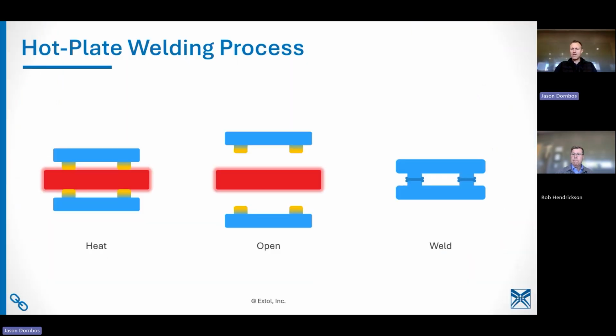How can you ensure that the weld will hold up to the impact from pallet jacks? Oh, that's a good question. So what we typically do, the testing that we can do is tensile testing, and we make sure that the weld is really, really strong. Hot plate welding, you can typically expect to get anywhere between 80 to 100% strength in the joint that you would expect from the parent molded material.